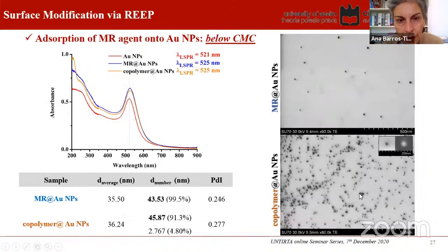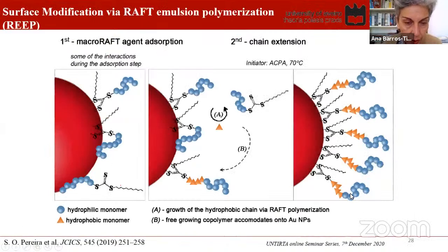So in view of this, we had to study the results using the macro RAFT agent below the critical micelle concentration. And in that case, yes, we have encapsulated particles that are individually encapsulated, as you can see, both just when they were coated with the macro RAFT agent and after carrying out chain extension with the hydrophobic monomers to form this hydrophobic shell. So working below CMC was the solution.